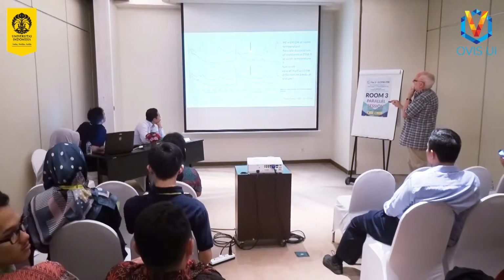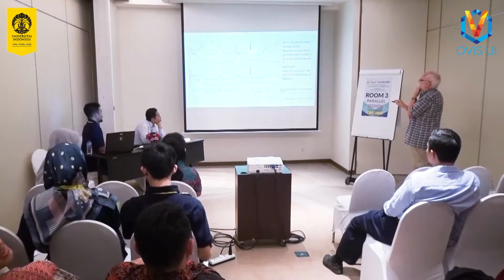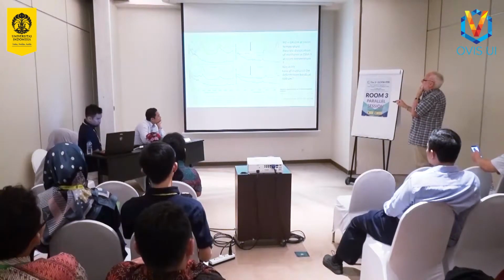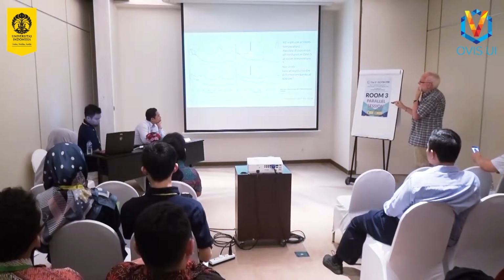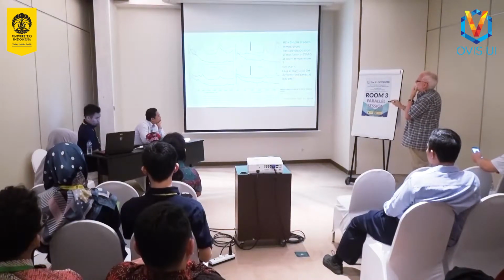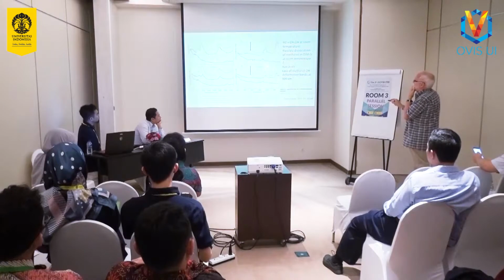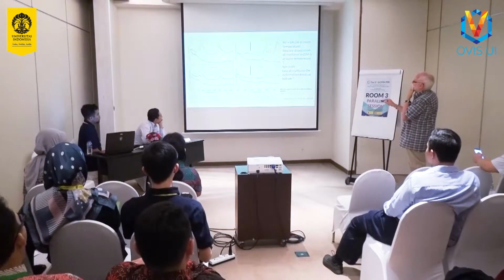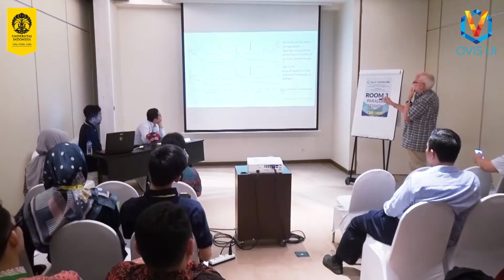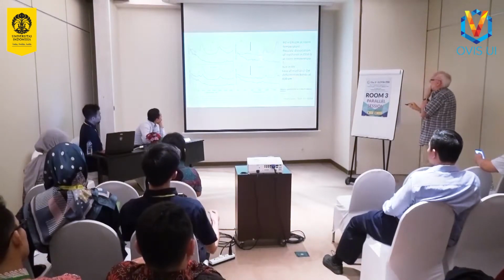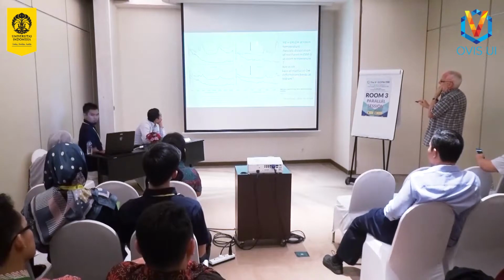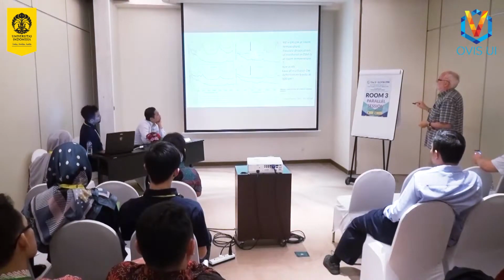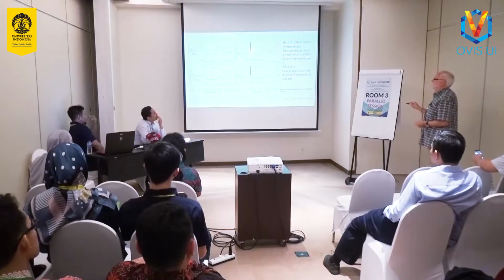These two bands here are OH bending modes of methanol. And you see, when it's absorbed in the zeolite, they are broadened out very much. Otherwise, the frequencies are about the same. That's the only major change. These have been measured with different spectrometers, so that's why the scales sometimes look a little different. So, the interpretation of that is that methanol is hydrogen bonded to the hydroxyl groups in zeolite Y.